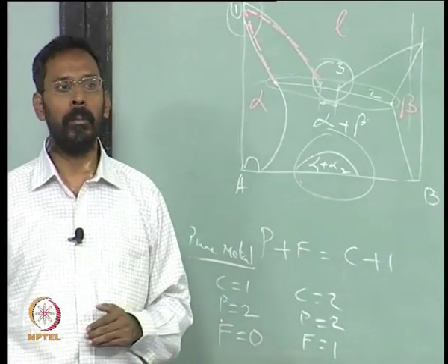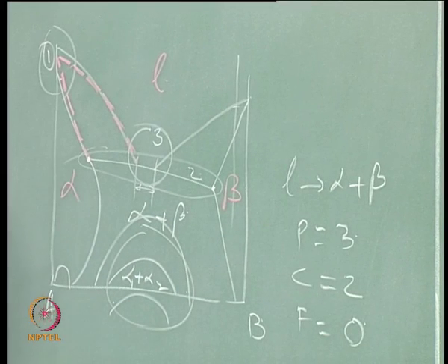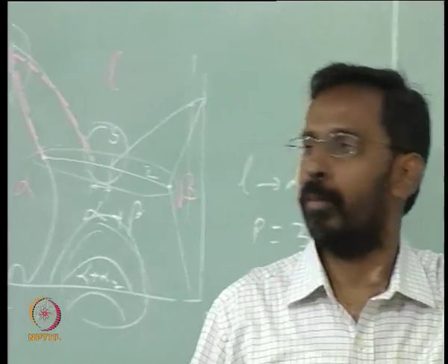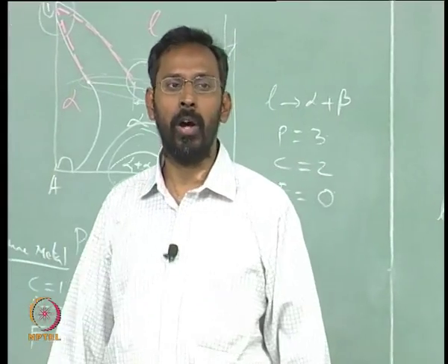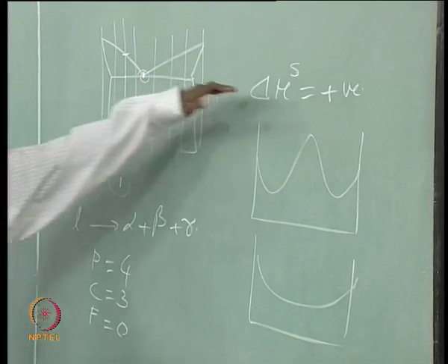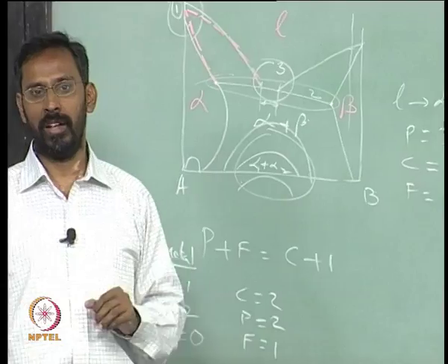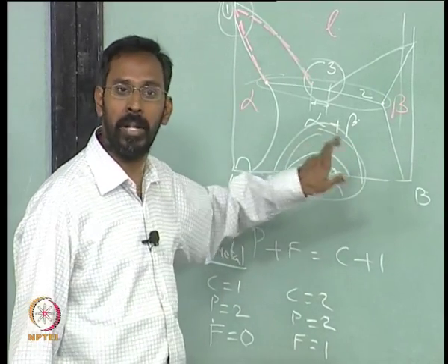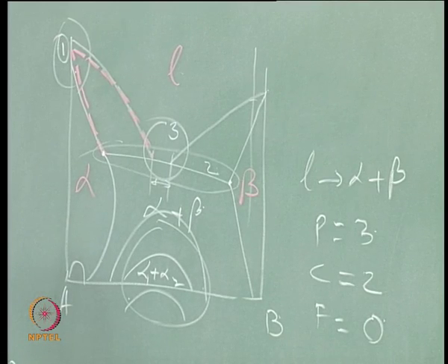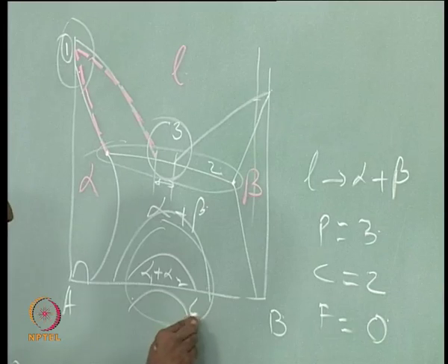This temperature that you are going to see, where the miscibility gap closes, the miscibility gap can close here, or it can close here below the room temperature, depends on the particular system, and it can happen when the delta H is very small. And if it is very close to 0, you may not have any miscibility gap at all. So, the moment you see a miscibility gap, it has to be there inside a single phase. Because the meaning of closure of miscibility gap means once I cross that, I have a single phase, and in this phase diagram I do not have a single phase. So, that is the fourth error in this.